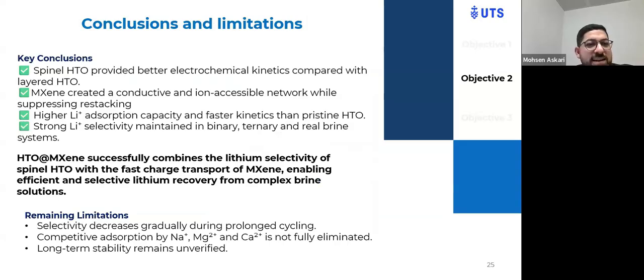The key conclusion here is spinel HTO provided better electrochemical kinetics for this target compared with the layered HTO. MXene created the conductive and ion accessible network while suppressing the restacking of HTO. Higher lithium adsorption capacity and faster kinetics than the pristine HTO were observed, and a strong lithium selectivity was maintained in the binary, ternary, and simulated desalination brine feed solutions. So HTO MXene successfully combines the lithium selectivity of the spinel HTO with the fast charge transport of MXene, enabling efficient and selective lithium recovery from complex brine.